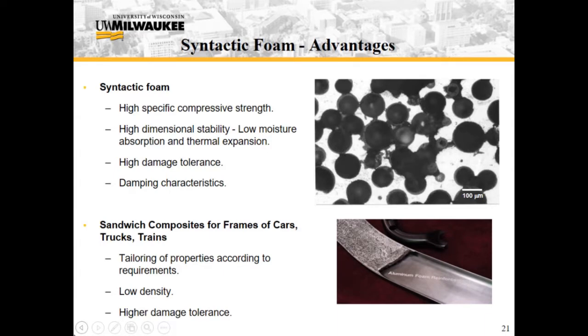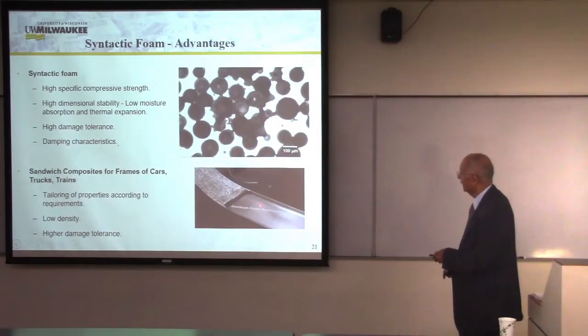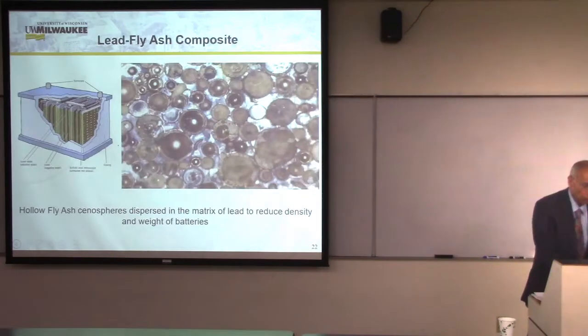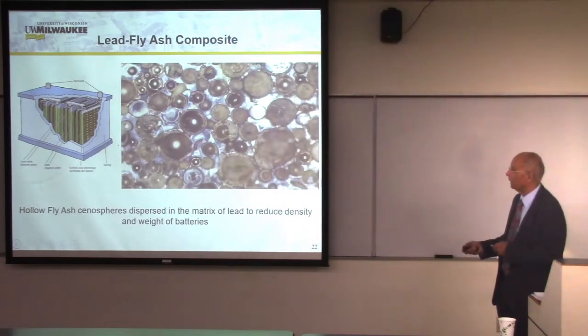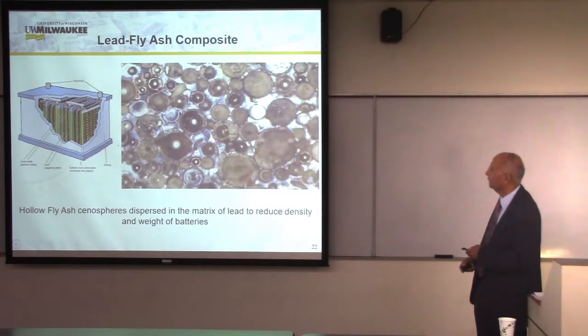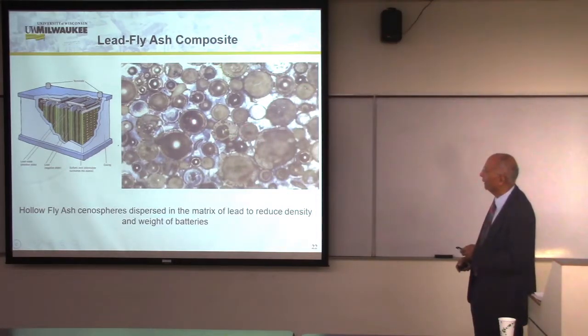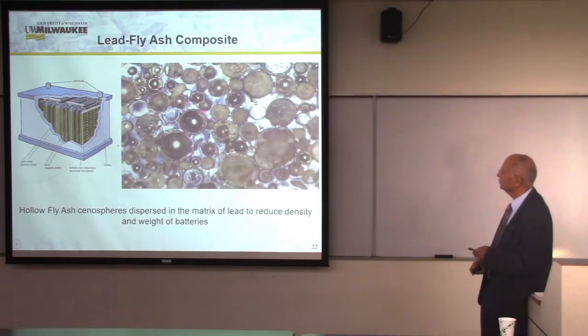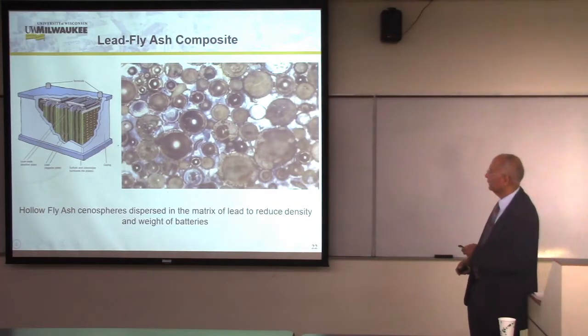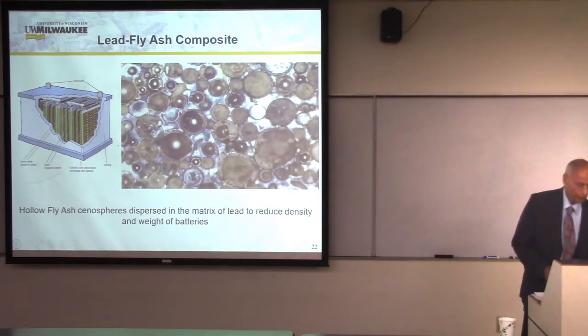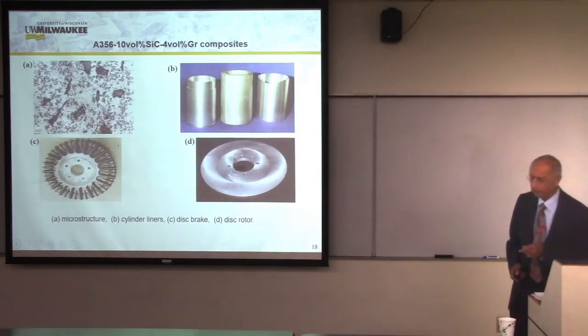The aluminum fly ash cenosphere syntactic foam can be encapsulated in hollow steel frames for transportation applications. So instead of using a solid steel, which is much heavier, I could use aluminum fly ash reinforced hollow steel frame to reduce the weight of the cars. You know, lead batteries are used in India a great deal and they are very heavy. So what we have tried to do is incorporate hollow fly ash cenospheres in lead to reduce the density of lead used in batteries to half. Of course, a lot more work has to be done to optimize this to make sure it functions properly in a lead acid battery, but the opportunity still exists.